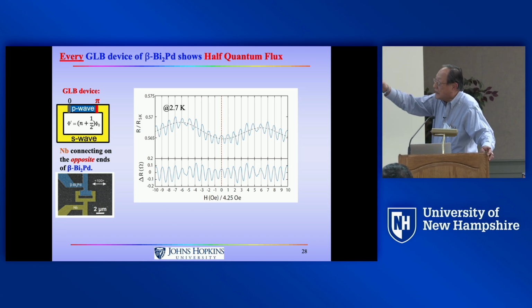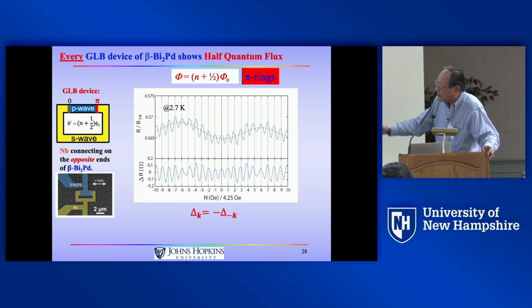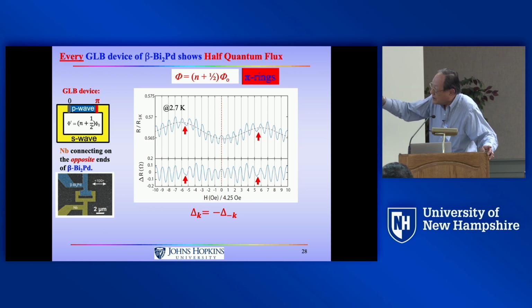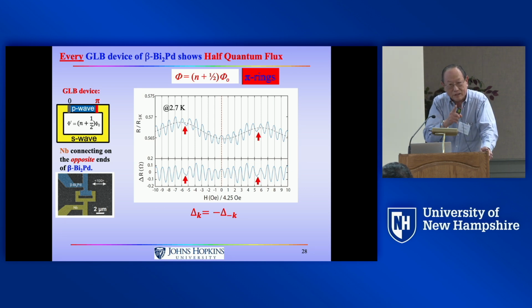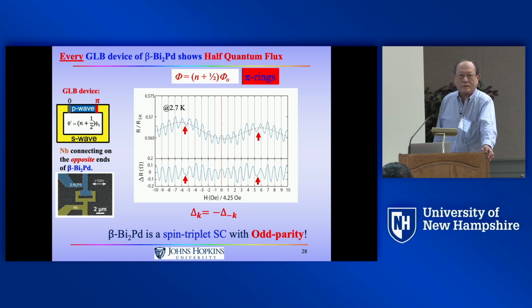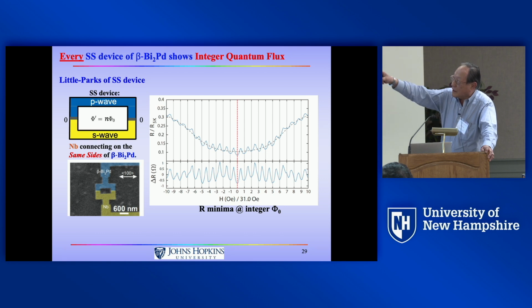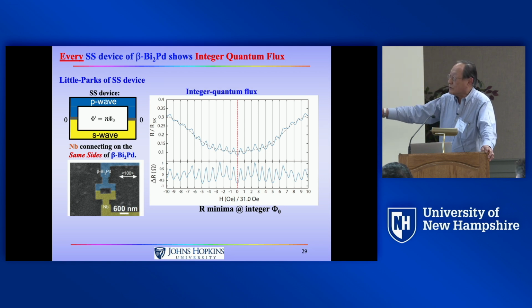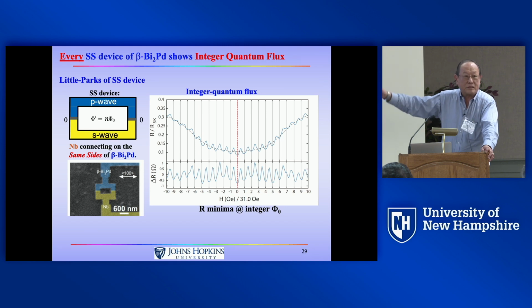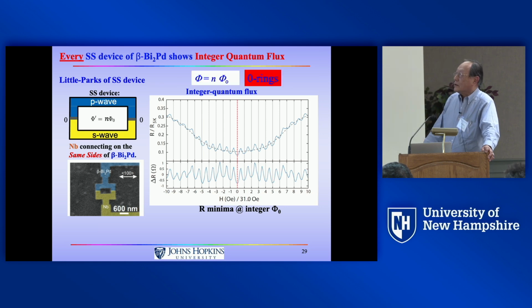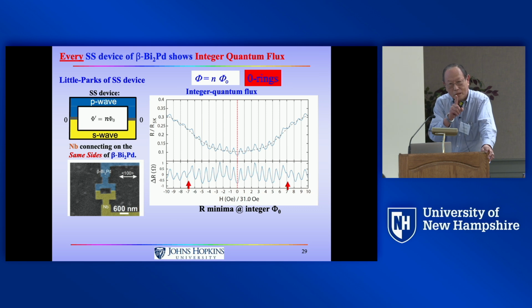Okay, you don't have to worry about, did I get the 0 correctly? You don't have to worry, okay? Because the ring has the imperfection. They show up on both sides. So it tells you where the 0 is, okay? Even though we know the 0 because this field is large enough, right? So 1 measurement we know. It's odd parity triplet. Now, if you connect to the same side, you actually know nothing. This is always a singlet, integer flux, because they connect to the same side. So now I do have a method to tell you I can definitely tell this is a singlet or triplet. 1 structure, 1 measurement.